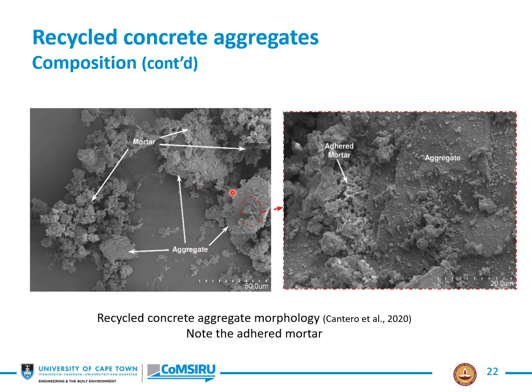There, in fact, is the adhered mortar here and the original aggregate particles. And if you just look at this section here, here is the original aggregate with some adhered mortar sticking to the surface and a whole lot more over here. And this is the material that we have to handle in terms of beneficiation.